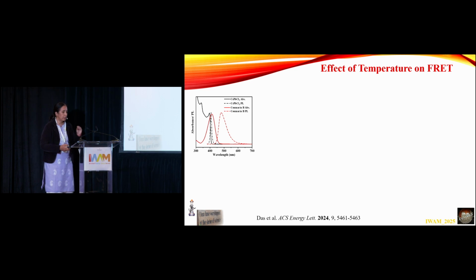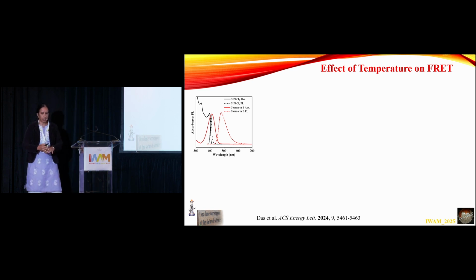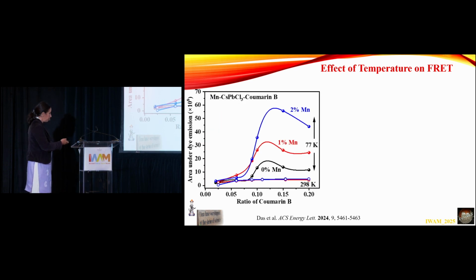But finally, the last thing that we did is, okay, if FRET efficiency is indeed increasing because of this, the last thing that I'm going to do is take the chloride system, and the chloride system, as I have been talking about, is not going to be vibrationally coupling with manganese at room temperature. So I should not see an increase in the FRET efficiency at room temperature, but when I go to low temperature, I should see an increase, and which is exactly what I observe here.